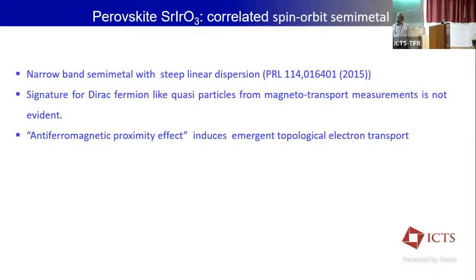So far, what has been known on SrIrO3, there have been some photoemission studies which show that this is a narrow band semi-metal with a linear dispersion. The ARPES data shows that there is an electronic band which has linear dispersion, but from transport data, there has not been any clear-cut evidence of this Dirac nature of fermions existing in this material.